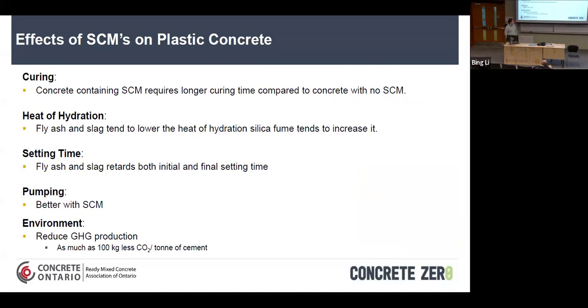So the effects of supplementaries in plastic concrete, you will have longer curing times, which is something you have to deal with in the field. So when they're building buildings, you have to take that into consideration. Your heat of hydration is reduced typically with fly ash and slag. With silica fume, it can often stay the same or increase the heat of hydration. The heat of hydration is how much heat is being produced when that chemical reaction of cement is occurring, and you get a certain amount of heat that gets produced by that chemical reaction.